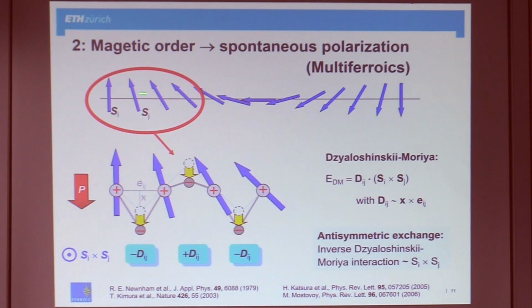That's always the same value because there's always the same angle of rotation between two sites, times the degree of asymmetry between two neighboring sites. The degree of asymmetry, so that's the source, the local inversion symmetry breaking is the source for the Dzyaloshinskii-Moriya interaction. And it's defined by this distance vector times the distance of this intermediate ion from this connection. So it's x, this deviation, times or cross this connecting vector.